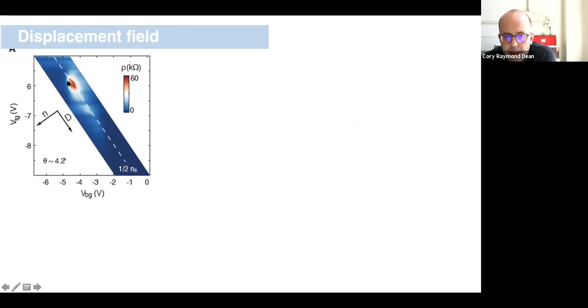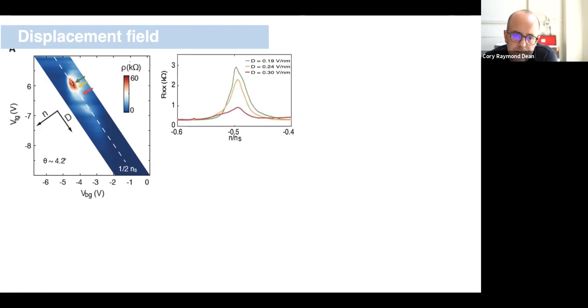And what we see is that this half band insulator really seems to stretch along the half filling point. So fixed half filling is along this dashed line here. But over a finite range of displacement field, it appears and then it disappears again.